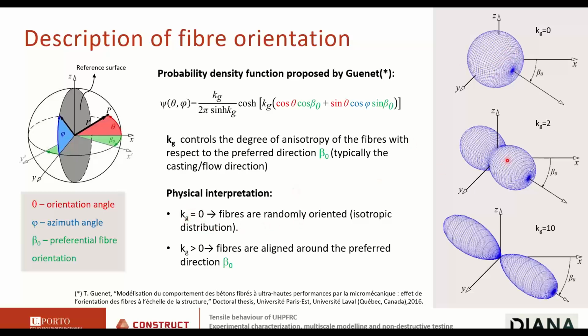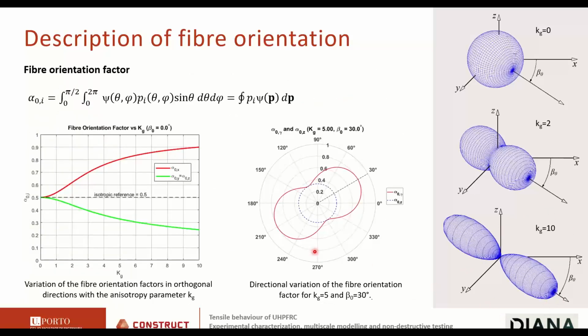As we increase the value of Kg, we start having preferential fiber orientation. So you see that the maximum radius, the maximum value of the probability density function, is achieved here, or 180 degrees to the other side. Okay, so these are different representations of the fiber probability density function for different values of Kg. This would lead to an isotropic behavior. The behavior is the same in all directions. Here it's anisotropic, and here it's very strongly anisotropic. So using some math, we can calculate the fiber orientation factor based on the probability density function of the fiber.